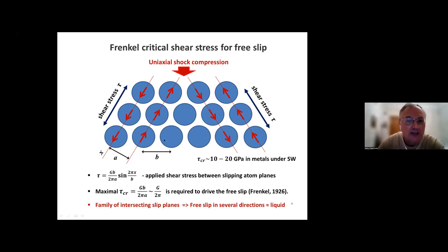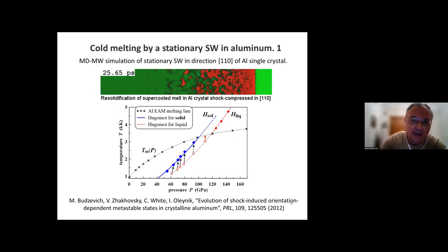So if such a condition happens, I mean critical shear stress is reached under shock compression, then what we may say, because there is a family of intersecting slip planes, free slipping may occur independently in different directions. It means that such a solid under this shear stress cannot resist the shear. It means it's just liquid. But as I said again, we have to confirm it by calculating